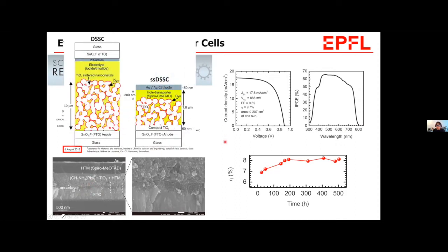The device resulted in a PCE of 9.7%, and more importantly, this substitution of the liquid electrolyte dramatically improved the long-term stability of the device, maintaining the PCE over 500 hours. It was a huge improvement compared to the previous one with the liquid electrolyte that only lasted some minutes. And in addition, thanks to the high absorption of perovskite, the thickness of the whole device was significantly reduced.